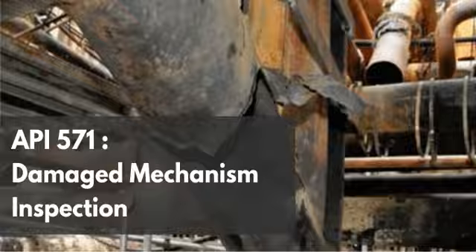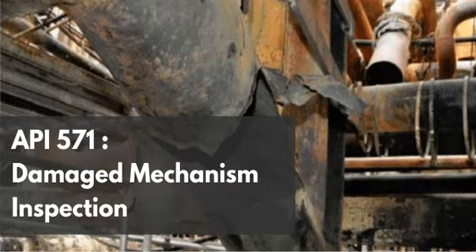Let's talk about the thick lip failure, because the physics behind that is just fascinating. It's a very specific signature. Normally, when a standard, healthy metal tube fails from overpressure or general thinning, it balloons out, right? The internal pressure pushes against the weakening wall, the metal stretches, it balloons, and eventually the edges of the rupture tear and stretch until they are razor thin. We call that a thin lip failure.